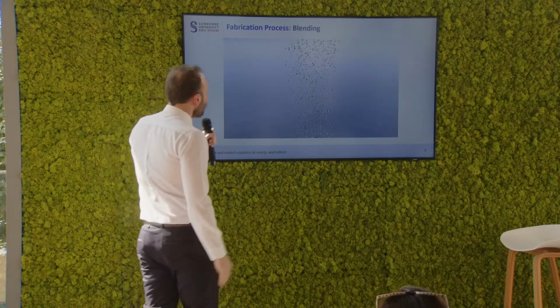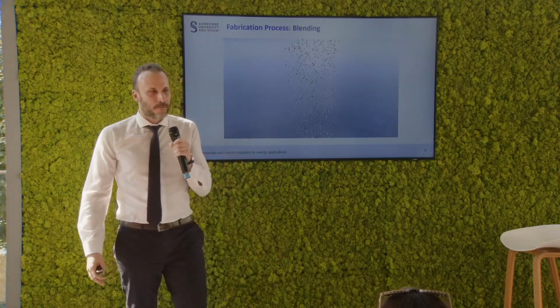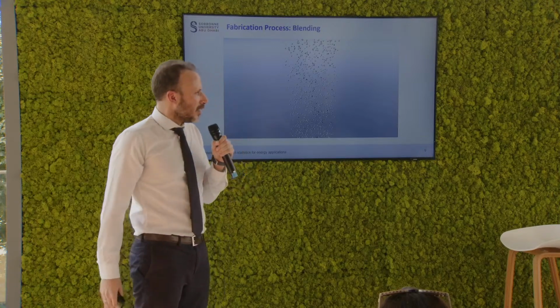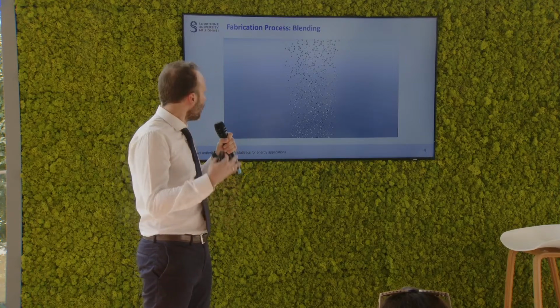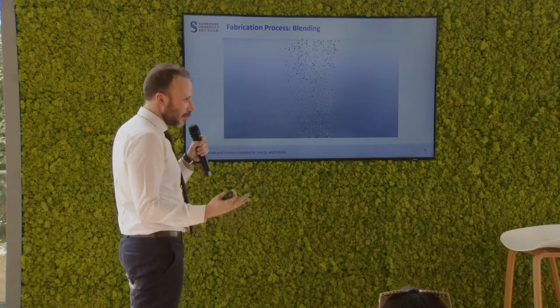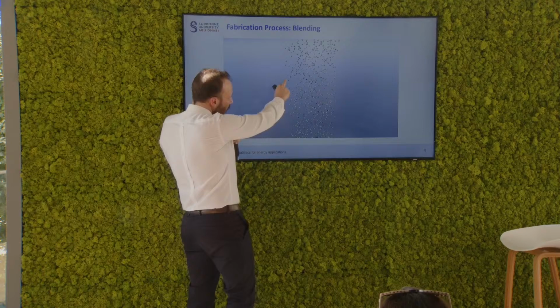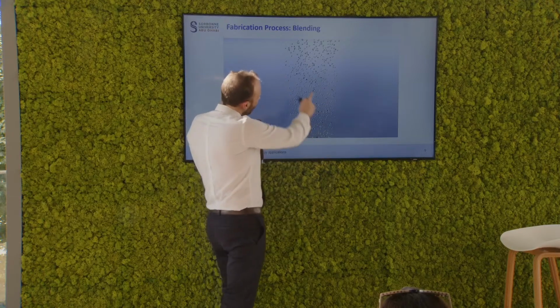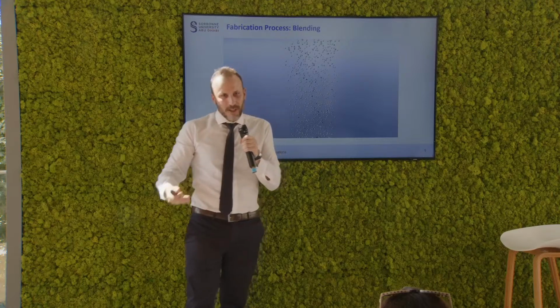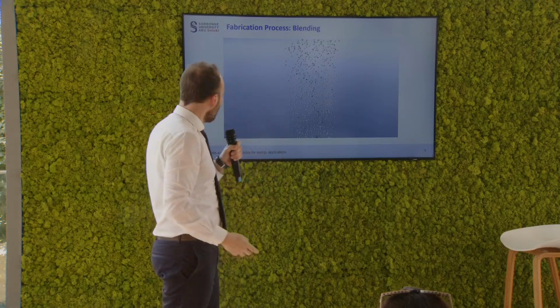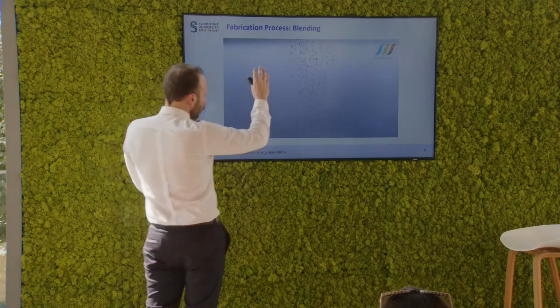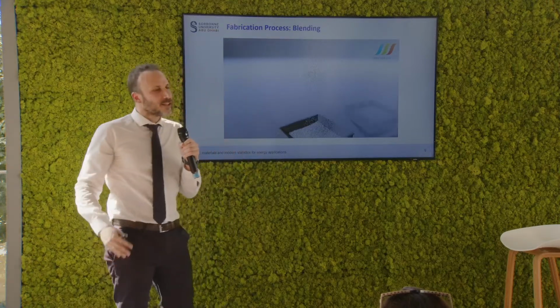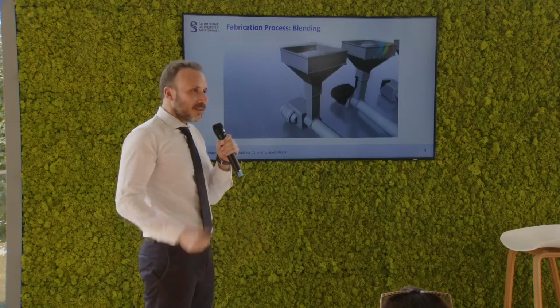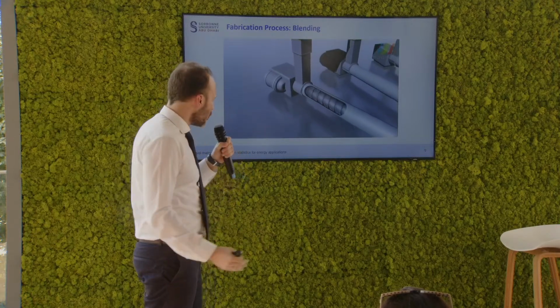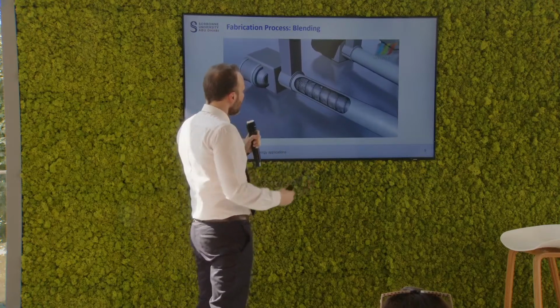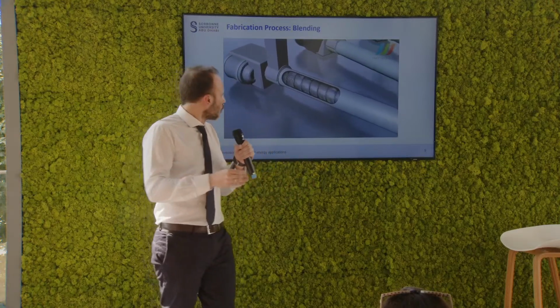So to help you visualize the process a little bit, I found an animation from a company called Muraplast, which will help you see the whole process in a much more direct manner. If you follow me here, the white dots is the polymer, whereas the dark dots are the granules that we have prepared through the process I've shown you before. So what happens in this case is that we feed all the particles inside an extruding device. Inside this extruder, temperature rises, pressure rises, so the particles are made to mix very well together, and the granules are breaking down to smaller bits.